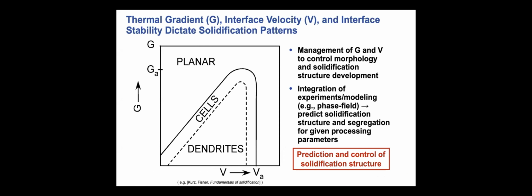So if you go ahead and you open a solidification textbook, you'll find a schematic diagram like this. This is from Kurz and Fisher. And basically our thermal gradient G and our solid liquid interface velocity V and different combinations impact the interface stability and also the morphology of the structures that we develop with solidification. So basically we can have a planar solid liquid interface, we can have the formation of scalloped cell structures, or we can make hierarchical dendrite structures that look like trees. And basically different combinations of G and V really impact the morphology of these structures that we develop.